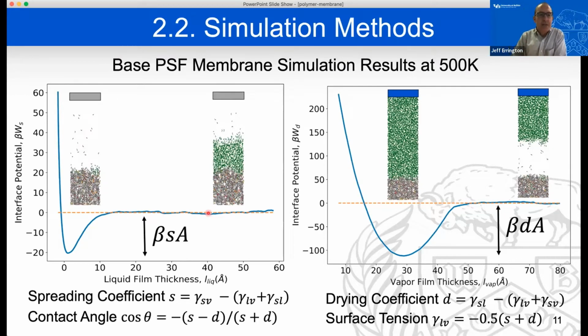In contrast, as we'll see examples later, if you have a situation in which this interface potential monotonically decreases and then plateaus out, in other words, there's no minimum, then that is a signature that the system is in the complete wetting regime. In other words, if you take the fluid and you put it onto the surface, it will spread evenly across the surface.